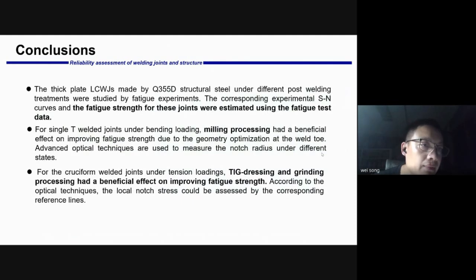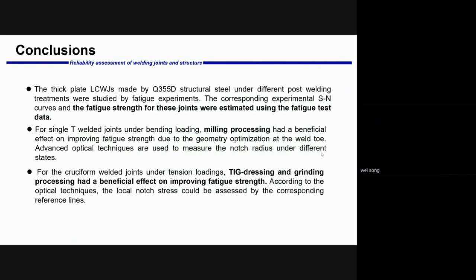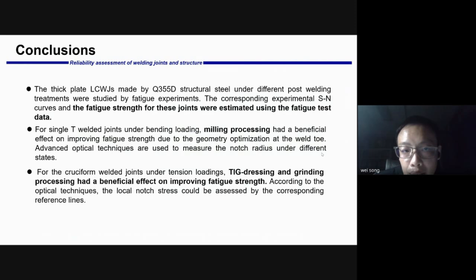Then we can get the conclusions. The thick plate LCWJs made by Q355D structural steel and different post-weld treatments were studied by fatigue experiments, and the corresponding experimental S-N curves and the fatigue strength for this joint were estimated using the fatigue test data.